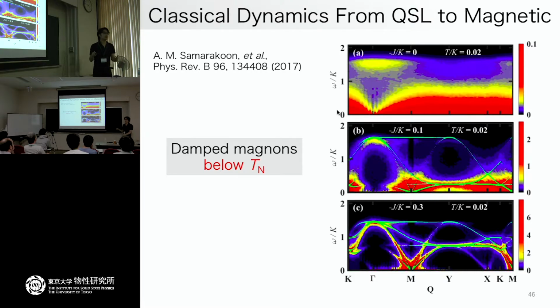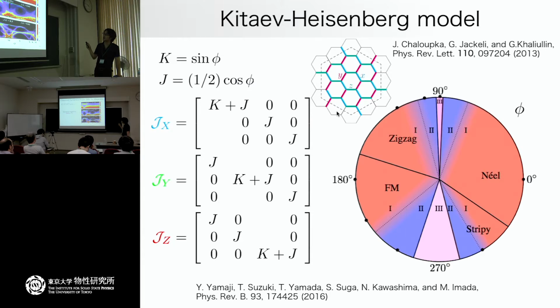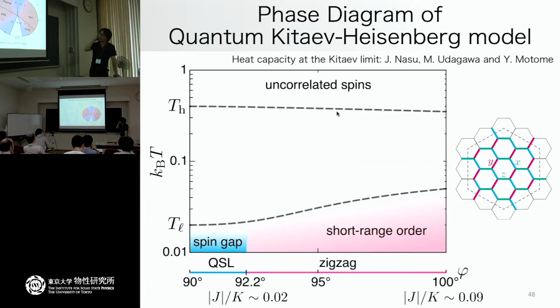Let me introduce some results from Professor Christian Batista's group. If we look at the classical spin dynamics in this region, starting from the Kitaev limit, and if you introduce 10% of the Heisenberg coupling to this Kitaev limit, then you will reproduce spin wave-like behavior. This green curve represents the spin wave structure, and this red part is the high intensity part of S(q, omega). Then if you move from the Kitaev limit to some ordered state, you will find damped magnons below the Néel temperature even in the classical phase. Please remember this situation. Then if we go to the quantum limit, I will show you what will happen.